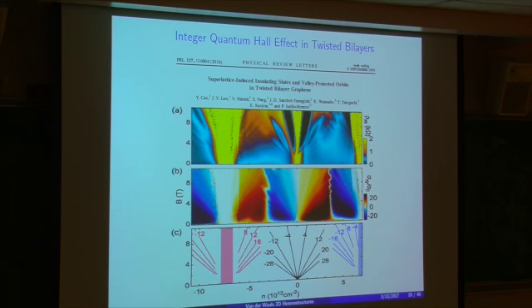And we can also look at what happens when we put now a bilayer of graphene with a tiny twist angle between the two. When we look at the magnetoresistance data, we will see also an interesting behavior. So this is the direct conductivity, and this is over here the Hall transverse conductivity. So we apply an electric field in this direction, and we get conductance in the other direction.